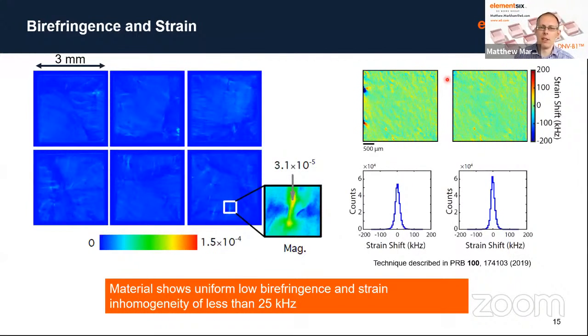We can go a little bit further, and this again is some more data from Ron Walsworth's group, where we took a bunch of samples. So this is 6 samples where we measured the birefringence of this 16 ppm material, and then they were able to do strain mapping. So it's effectively looking at the ODMR line positions across the entire sample. So this is a 500 micron bar here.